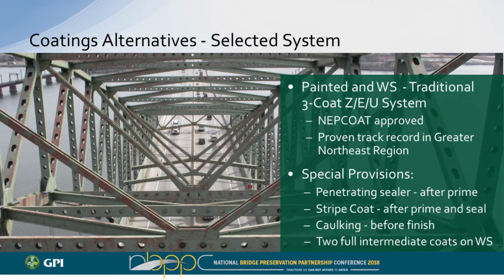We also had a stripe coat. The stripe coat also went in after the primer. It went in also after the penetrating sealer if that was applied. Now the stripe coat was basically all faying surfaces, so rivet heads, all angles, say if you had a web plate and a flange angle, anywhere that there was a gap or an overlap rather, we had the stripe coat applied. And again, brush or roller applied to make sure we got that coverage.